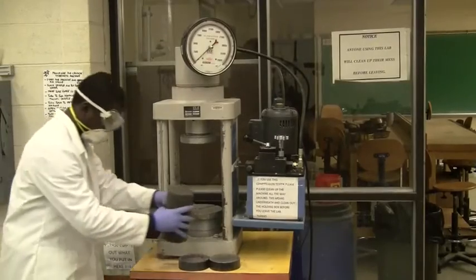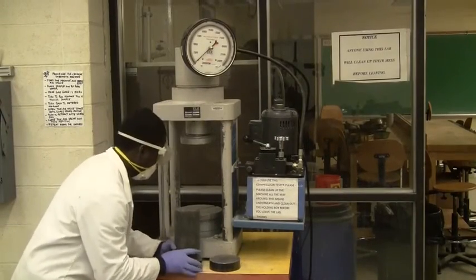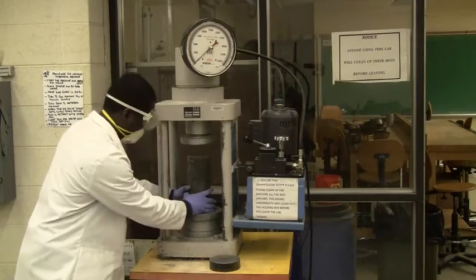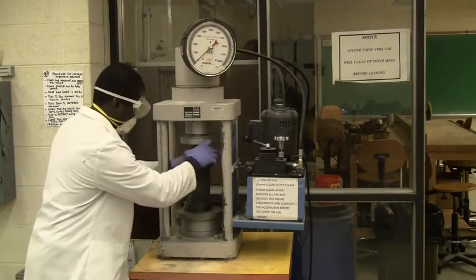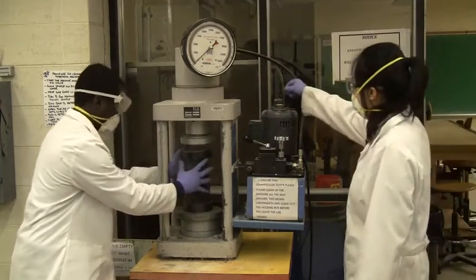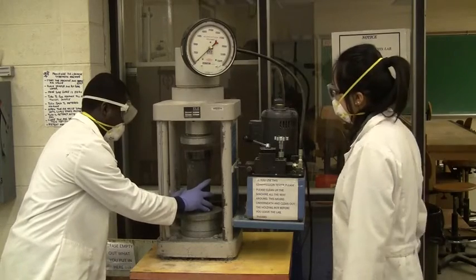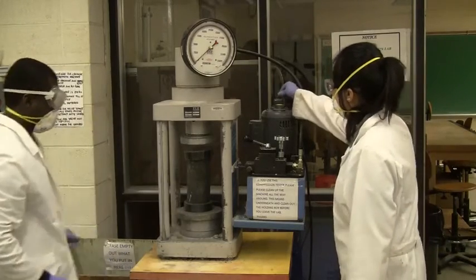Place the cylindrical sample in the middle of the compressor. Start the compressor and carefully track the strength on the gauge meter. When the sample failed in compression, the peak strength that the concrete can be held is recorded on the meter, which is the ultimate compressive strength.